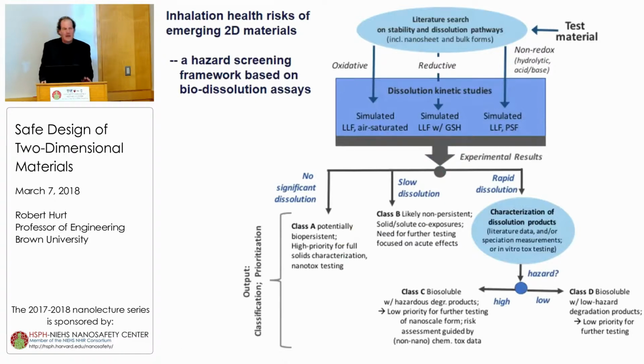It could be simulated lung lining fluid, which you would want to keep air saturated if the material was susceptible to oxidation. If it's susceptible to reduction, we would suggest simulated lung lining fluid with GSH addition. And you'd have to replenish the GSH to make sure it doesn't get oxidized by the air or by the material. And if it's a non-redox system, you could use simulated lung lining fluid. And we might also suggest you use phagolysosomal simulant fluid to model the effects of the different pHs, both in the intracellular and extracellular compartment. And based on what you get, you may see rapid dissolution, slow dissolution, or no dissolution.